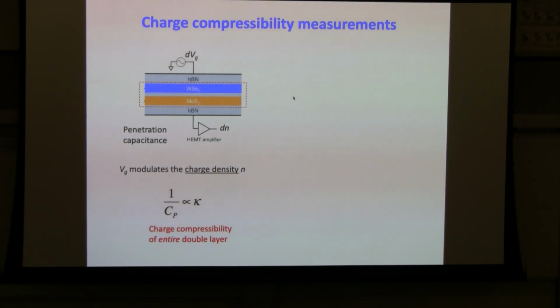All right, so the first experiment that I will show is a charge compressibility measurement, which tells you whether the double layer structure is in an insulating state or in a metallic state. What we do in this measurement is apply a small AC voltage to the top gate, dVG here, and measure the displacement current or the charge that we collect from the bottom gate here. This is called a penetration capacitance measurement because we measure the capacitance of the electric field that penetrates through the sample.